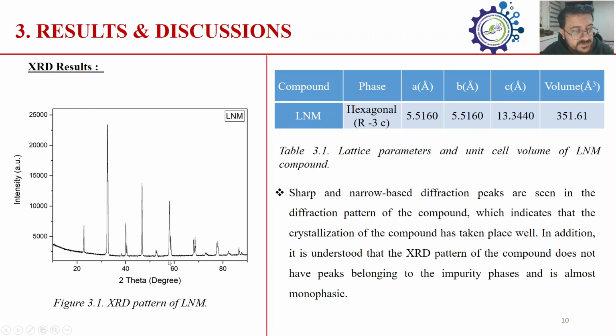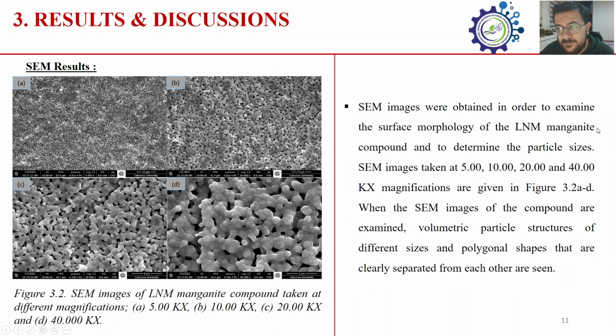This figure shows the XRD pattern of LNM, and this table shows lattice parameters and unit cell volume of LNM compounds. According to the XRD result, LNM has a hexagonal phase, and sharp and narrow-based diffraction peaks are seen in the diffraction pattern of the compound, which indicates that the crystallization of the compound has taken place well. In addition, the XRD pattern of the compound does not have peaks belonging to an impurity phase and is almost monophase.